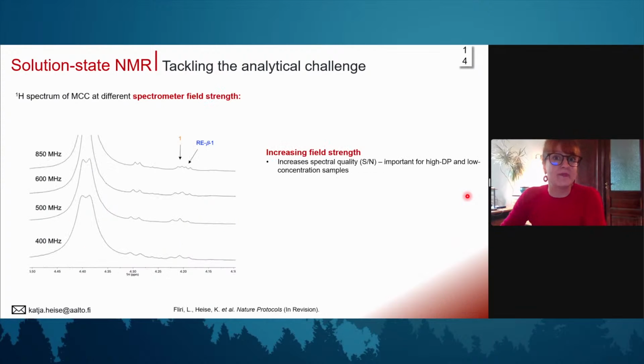Okay, one other important aspect, if you are thinking of using this method and have a spectrometer available, is whether it is suitable. What is important for the result that you get for your spectra is the spectrometer field strength. So Alistair has tested different spectrometers from 400 megahertz to 850 megahertz. And of course, if you increase the spectrometer field strength, you increase signal to noise and your spectral quality.